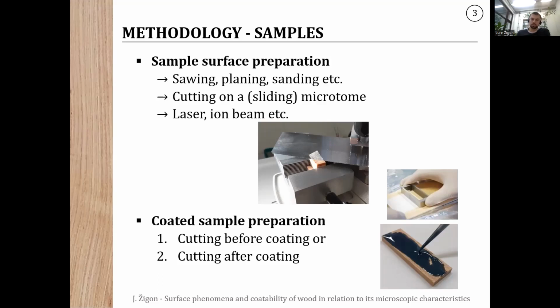Mostly I'm using the cutting on a sliding microtome, which we can see on the photo. This is, of course, the destructive method, but it makes the surface very smooth and proper for observation. Other, more sophisticated techniques are laser and ion beam irradiation, but up to now I didn't use these, though they are possible to be used.